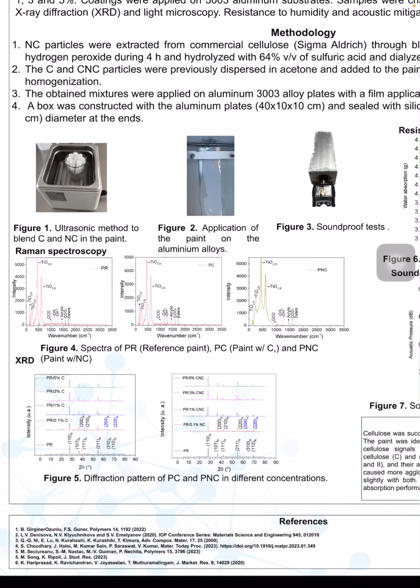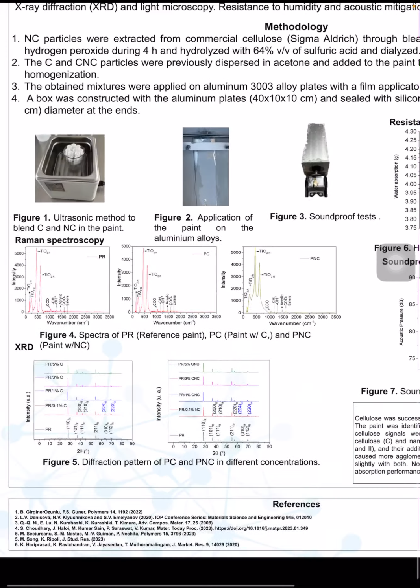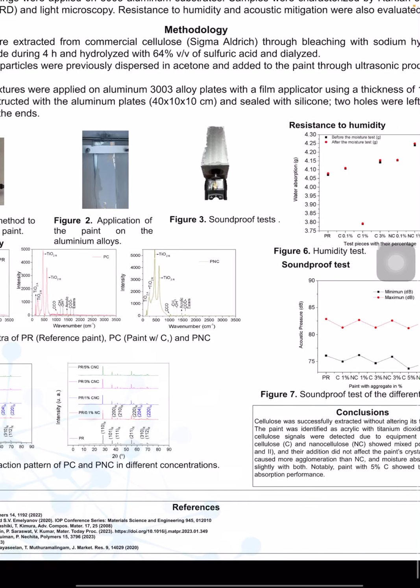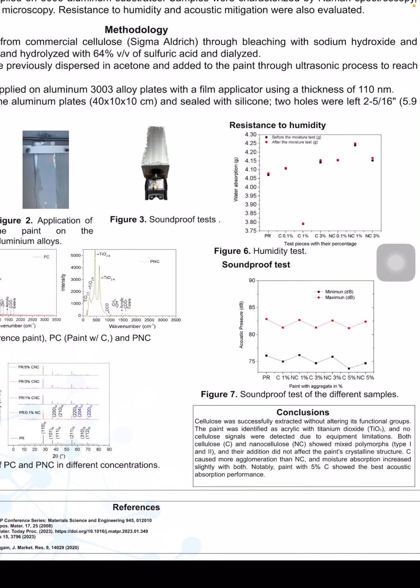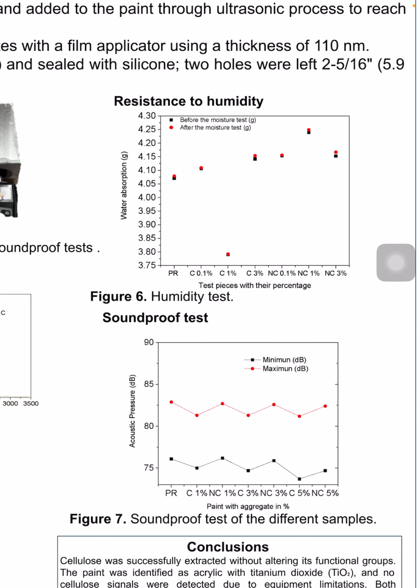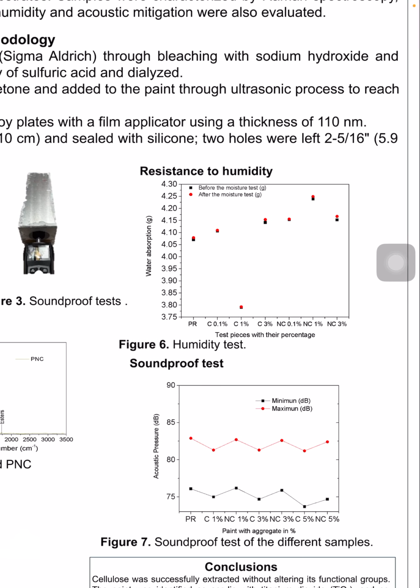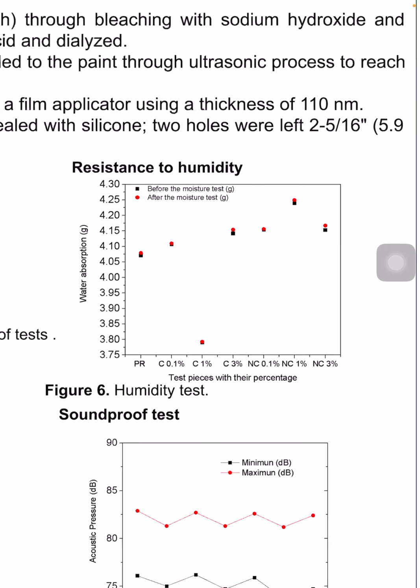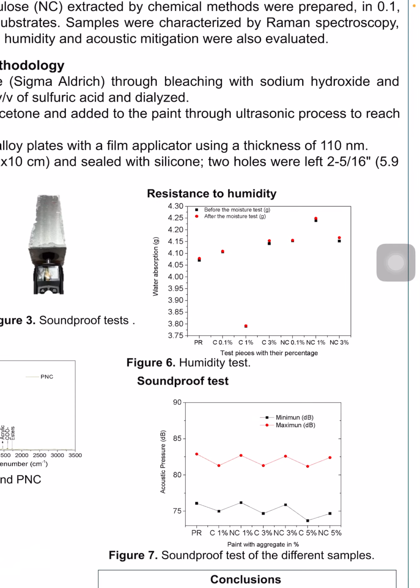So we can confirm that it's still the same. We cannot see any changes with the addition of either cellulose. In the water absorption, we can see that adding a higher percentage of cellulose and nanocellulose increases the absorption of humidity of this paint. In this case, the lowest absorption we can see is the cellulose 1%, but in the other samples the absorption still grows.